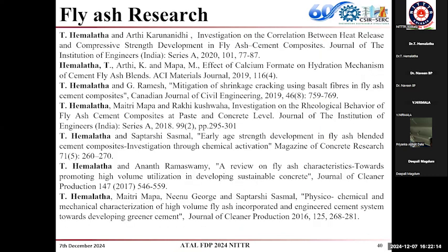And these are some of the literature wherein we have studied how the fresh properties are affected, because of the rheological property, if we want to develop self-compacting concrete. Self-compacting concrete has the advantage that it can even penetrate through congested reinforcement. We don't want any mechanical vibrator for vibrating such concrete. When we want to develop such self-compacting concrete, the incorporation of fly ash provides flowability to the concrete, and we can easily get self-compactability. So it is the rheological behavior we have studied.